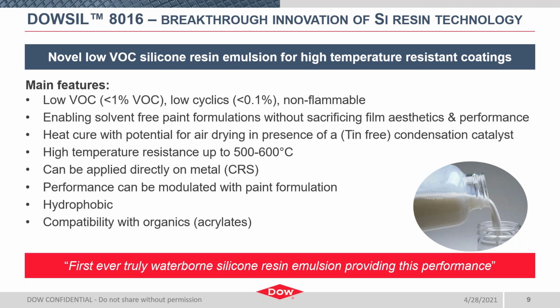Beyond the clear EHS benefits, DOWSIL 8016 waterborne resin provides high temperature resistance and can be applied directly on metal with excellent adhesion. And paints we've made with the 8016 have yielded very hydrophobic films, which of course is advantageous to minimize the generation of corrosion in those heavier duty applications. Our R&D team has developed a model paint formulation, but we recognize, of course, tweaks will be necessary to achieve variations in the required performances, as the binder is only one component of a paint.